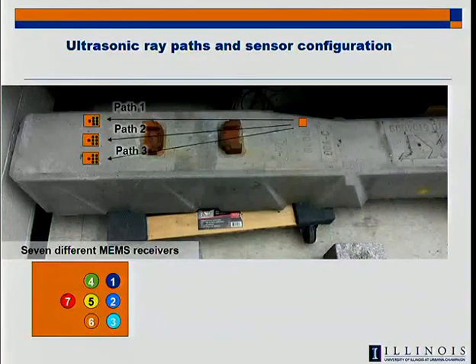So basically, what you'll see here is one sender, and then we have different receiver sets to see if the path makes a difference. And as you can imagine, path one, the path that does not interact with those steel collars at the end of the rail seat, has the most usable large signals, because these act to reflect energy quite a bit, because they extend into the surface, and the surface waves are kind of reflected from that. We can still get information. It's not as useful, however.